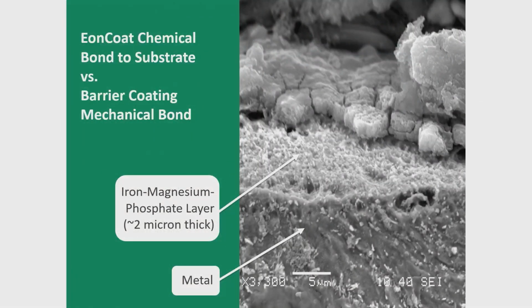This is a more detailed scanning electron microscopy picture of what this looks like. What you see here is we scraped off the ceramic and we're looking at just the alloy layer. And it's not thick, it's only a few microns. But compare it to the layer on stainless steel, which is angstroms, you're talking thousands of times as thick.